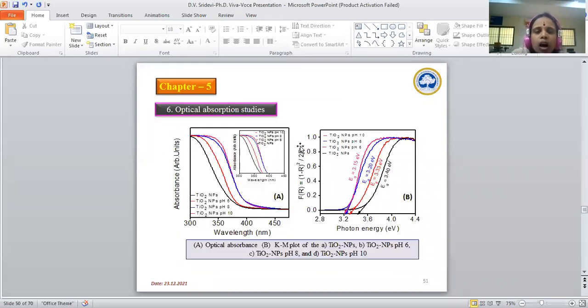This slide shows optical absorption spectra for TiO2 nanoparticles at various pH levels. The absorbance was observed near the visible region. This is due to the charge transfer from the valence band to the conduction band. Then figure B shows the Kubelka-Munk plot of titanium dioxide nanoparticles at various pH. The band gap value for titanium dioxide was found to be 3.4 electron volts. When the pH value increases, the band gap values decrease from 3.33 electron volts to 3.15 electron volts, which is shown in figure B.